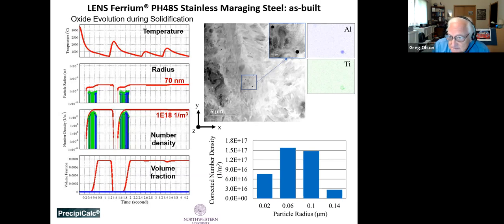And this is the one attribute of microstructure that's sensitive to that early process history that is retained throughout the rest of processing. In particular, where it's advantageous is these very stable oxides are a good grain refining dispersion during the very high temperature HIP consolidation that we apply to these 3D printed materials. So we can keep reasonable grain sizes after HIP consolidation. So pretty extreme.